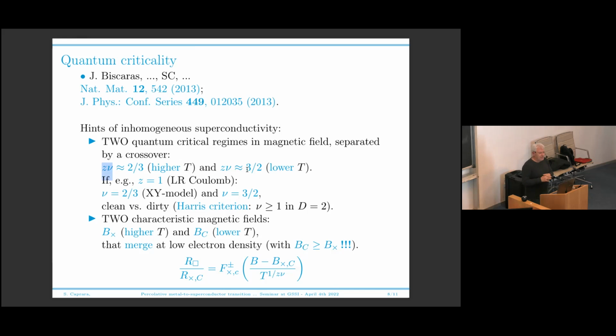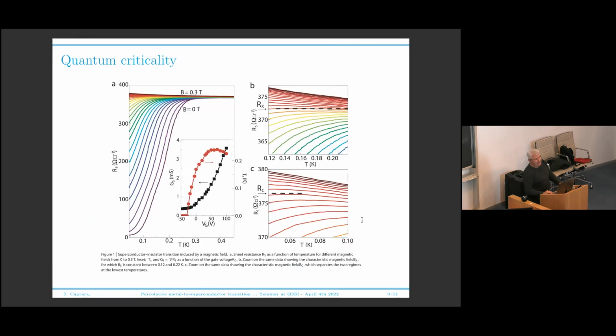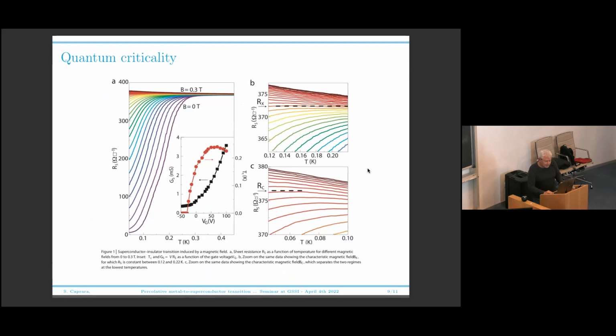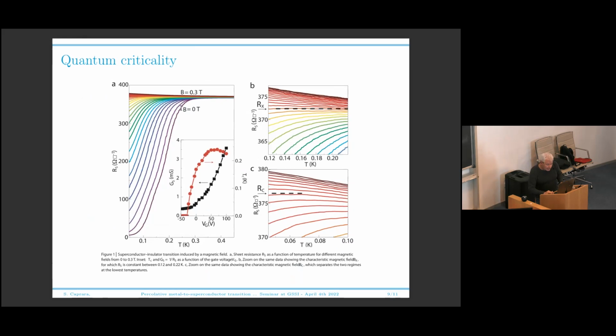And those two regimes correspond to two different magnetic fields, one which we call the B cross and the other that we call BC, one that is seen at higher temperature and the other that is seen at lower temperature. And what is even more interesting is that BC, the one that you see at lower temperature, is larger than B cross, the one that you see at higher temperature. So this is a typical set of data. Here, you see that you are in the superconducting state when the magnetic field is zero. You increase the magnetic field, and you gradually turn your superconductor into this weakly localizing metal.